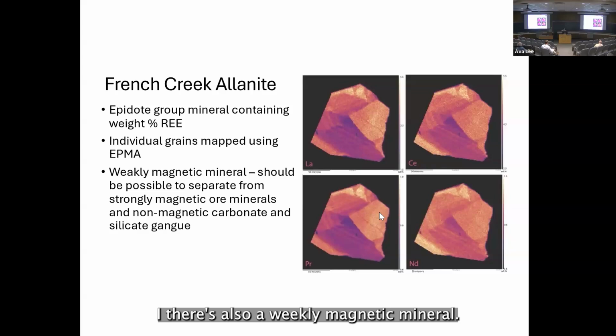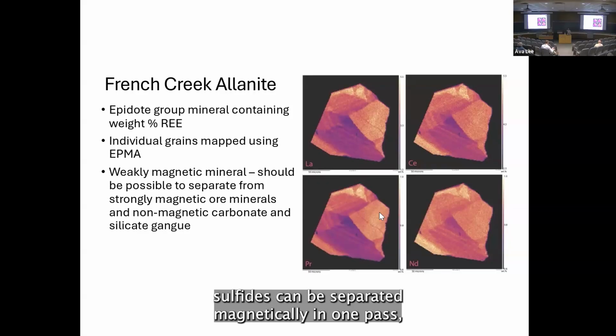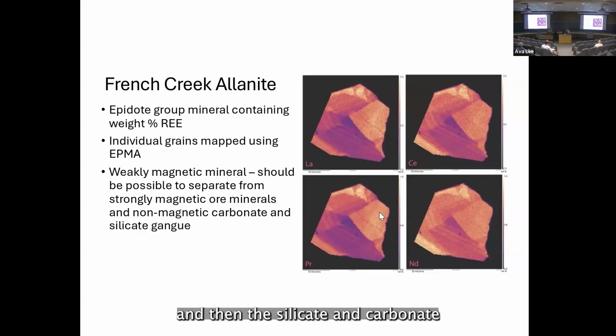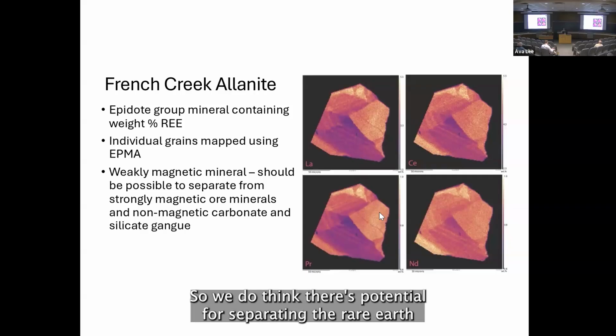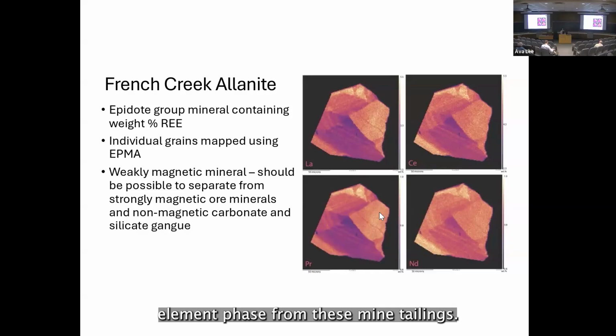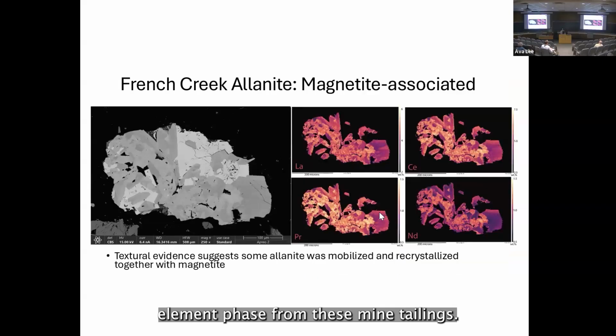Allanite is also a weakly magnetic mineral, so in comparison to the highly magnetic magnetite and sulfides, it can be separated magnetically in one pass, and then the silicate and carbonate minerals can be separated out in another pass. That should leave us with a strongly epidote enriched middle segment. So we do think there's potential for separating the rare earth element phase from these mine tailings.